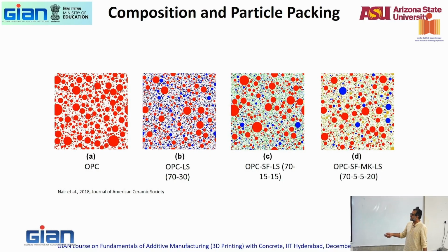Here is a system with 70% cement, 15% silica fume, and 15% limestone. Silica fume is even finer than limestone. What happens to the packing density of this system? Even finer, even higher, most closely packed than this, right? And you see here, what have I done? If you simply look at the cement grains, I have spread the cement grains farther apart. I have reduced the amount of cement in the system.